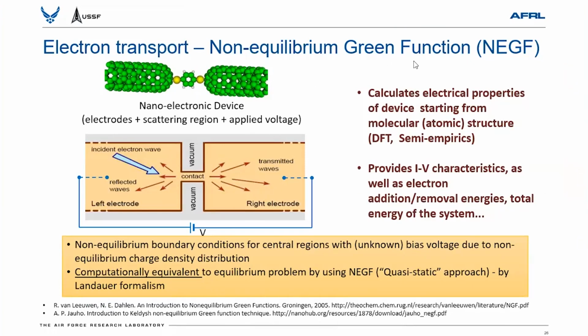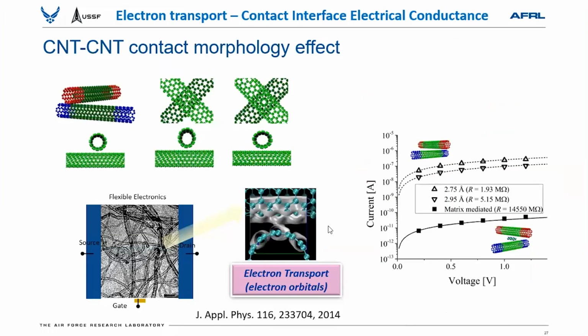Now, the final topic: the electrical property that we looked at at the interface by tight binding non-equilibrium Green's function, and we have published this work. You can follow it. Because of time, I'm not going to talk about the methodology. But what I'd like to say is, in this junction design for electrical conductance at the interface, electron orbital plays a role. Overlap of electron orbital dictates the electrical conductance. If you make the carbon nanotube smaller, their electron orbitals repel out of the circumference, hence the higher overlap. And that's what we observe.